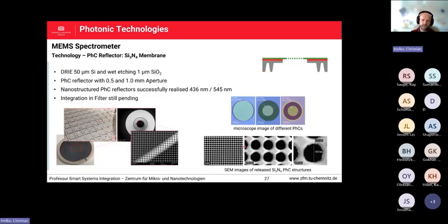And at the final end, as already mentioned before, we did from the backside here, the gray one, which was closed, 50 micrometer silicon etching and 1 micrometer silicon dioxide etching, so that the membrane here, the green one, was then freestanding. And we realized 0.5 millimeter and 1.0 millimeter apertures, meaning freestanding membranes filled with all of these fancy nanostructured holes. And here again, a wafer from the backside with these cavities and all these colored nano reflector apertures. Here a side view, and here some SEM images showing all of these small holes of this fabricated reflector itself. So it works quite well.